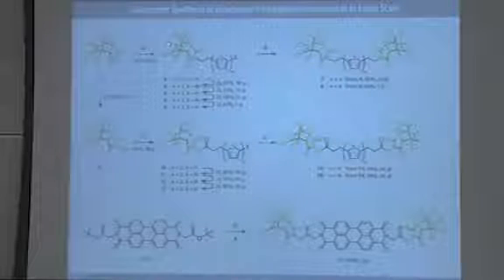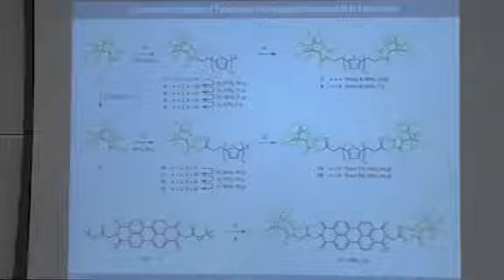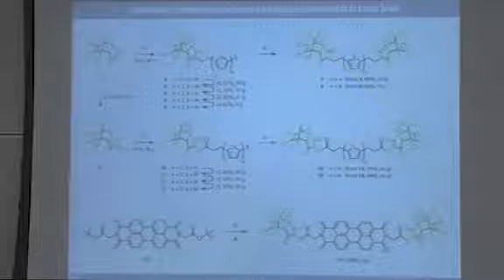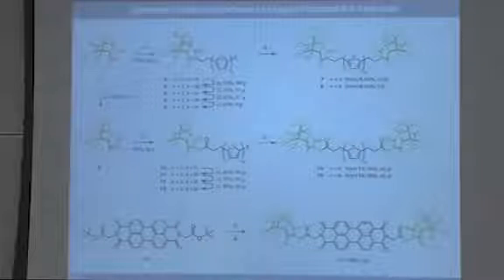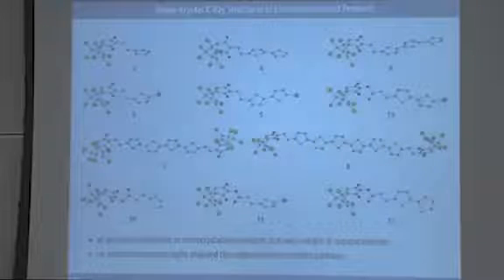And so we use the chlorendic acid anhydride as both an imide protecting group for a terminal amine and an active ester protecting group for a terminal carboxylic acid. And as you can see, because now all products are crystalline and at the same time they're highly soluble in organic solvents, I'll comment on that on the next slide as well, we could perform easily in our regularly equipped synthesis lab these syntheses on the multi-dozen gram scale, even towards the final compounds. And we also made use of the same style of protecting group for the perylene bisimides, which we then could further functionalize. And so that gave us a toolbox of oligothiophene and perylene bisimide diamines and dicarboxylic acids for further functionalization. And as I said, all these compounds are nicely crystalline. Actually, they typically precipitate from the reacting mixture upon simple cooling after the reaction.